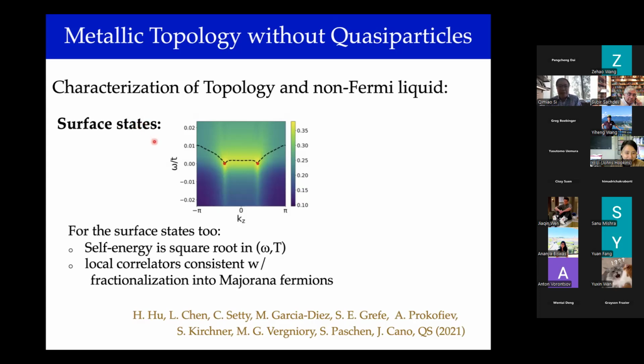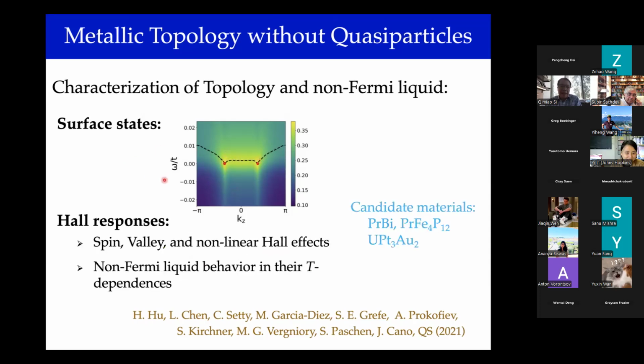And we did a calculation for this model to show that there are indeed Fermi arc-like surface states. But again, if one probes the spectral properties of these Fermi arc states, they have non-Fermi liquid form, and based on the calculation of local correlation functions, it behaves similarly to the bulk excitations. It's in a form that's consistent with fractionalization. The bulk for two-channel would be fractionalized into Majorana fermions. The three-channel Kondo lattice would be fractionalized into parafermions. And for the surface states, we observe very similar local correlation behavior as a function of temperature and frequency.